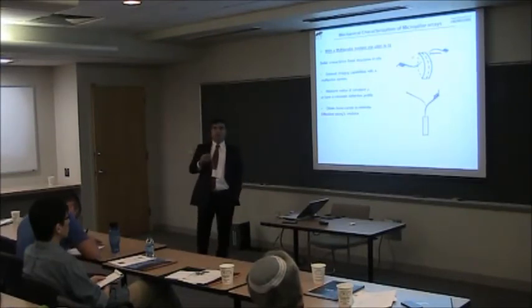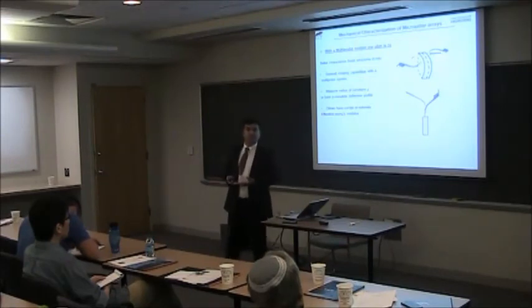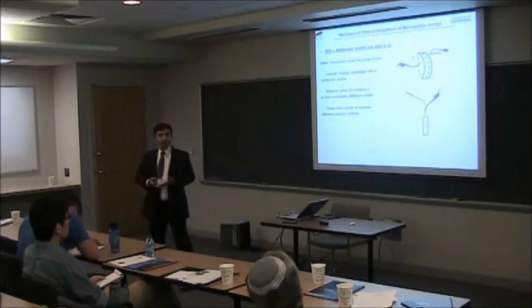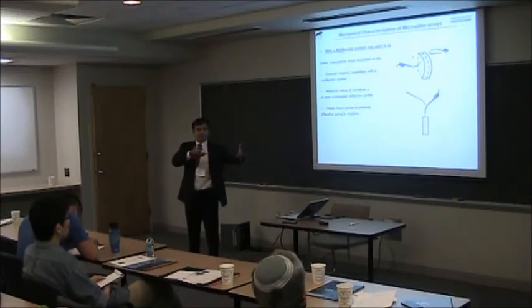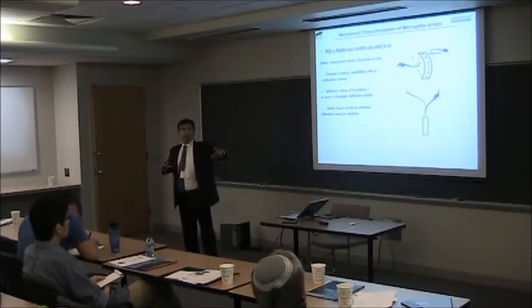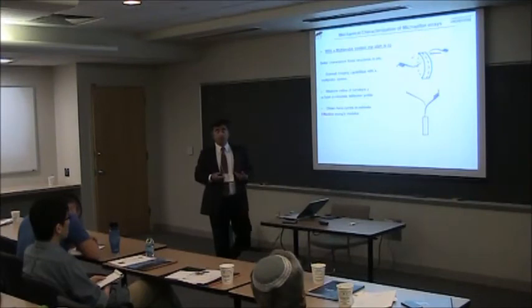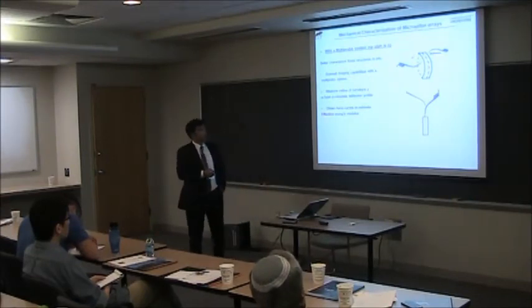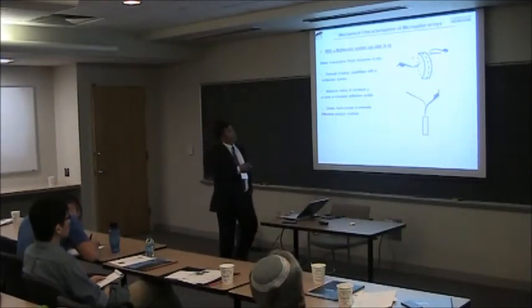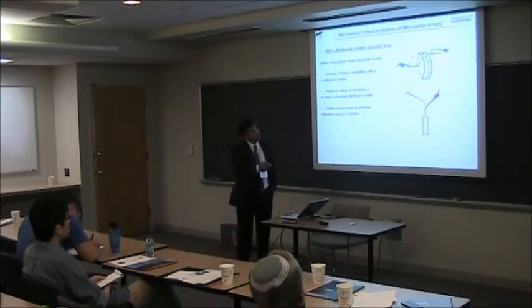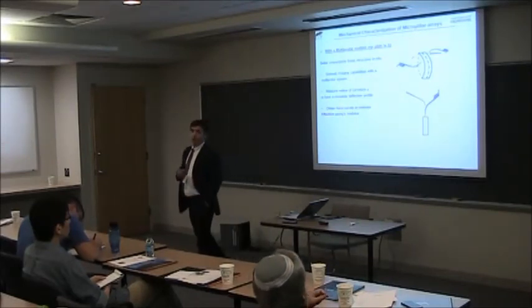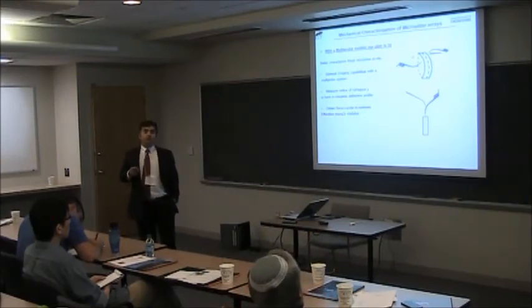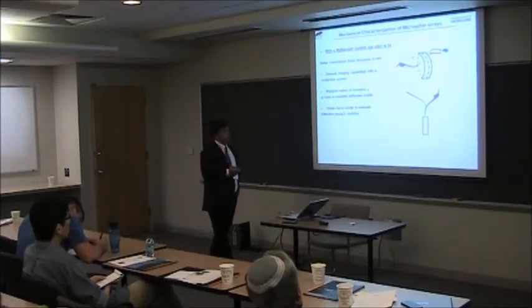And I want to measure the Young's modulus of that specific pillar structure so that I can measure the deflection that the cells create, and then calculate the forces for those pillar sets. So we were talking about pushing the pillar from one side and then coming with a second probe and measuring the curvature, which would give you the most accurate readings if we can make it. Of course, there are limitations.